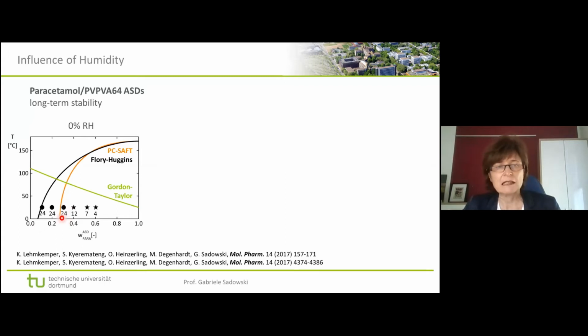And then to verify what the real experimental result is, we have spray dried formulations of these two components, the polymer and the API, at different API contents. You see we have six samples. And then we store these samples at 25 degrees centigrade in a dry system, so really no relative humidity. And then you have the symbols here. Stars mean that the samples crystallized, that we did find crystals in the samples, and circles mean that we did not find crystals. And according to the solubility line, no sample left of the solubility line should ever crystallize.